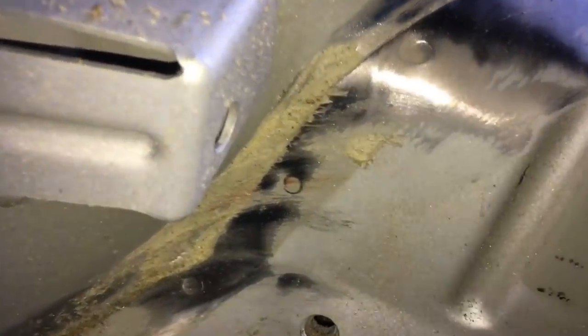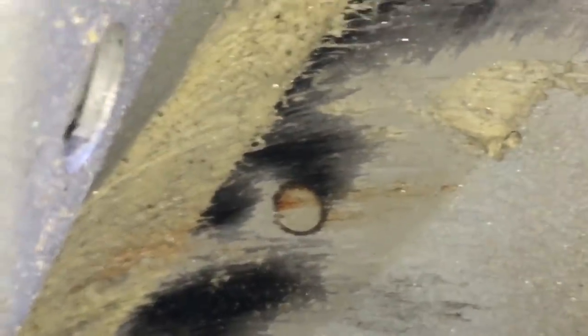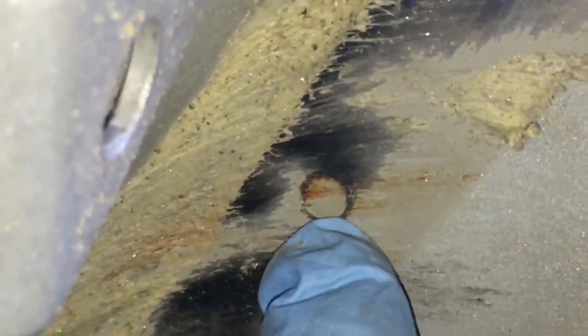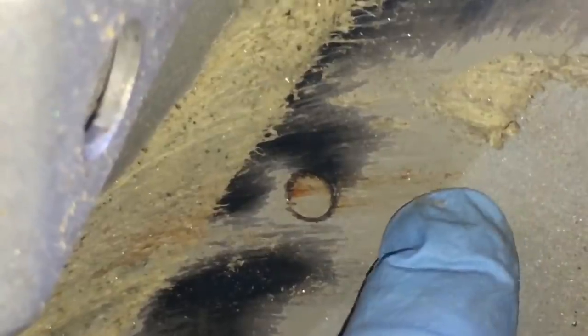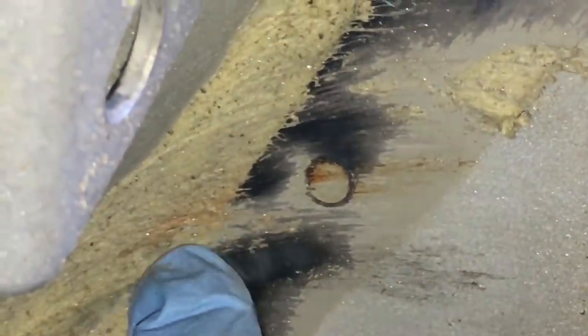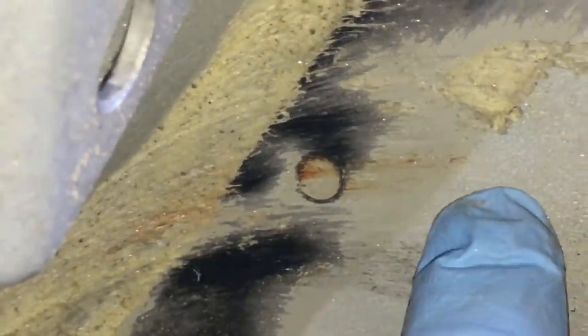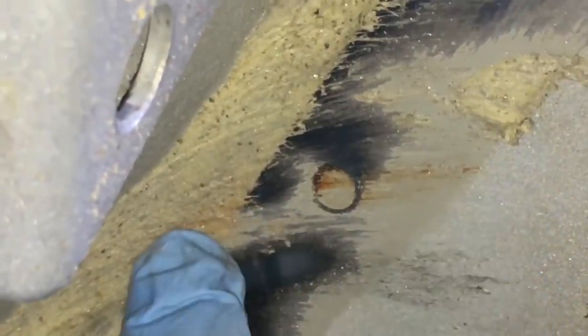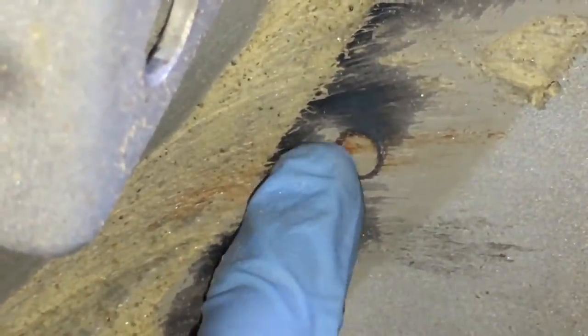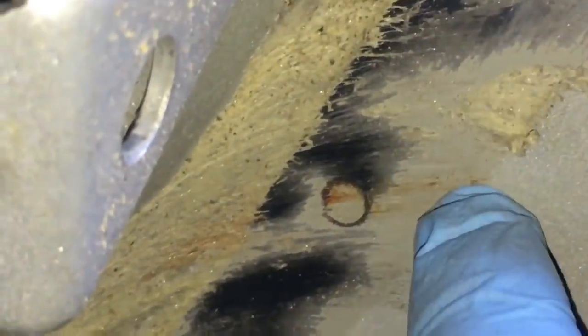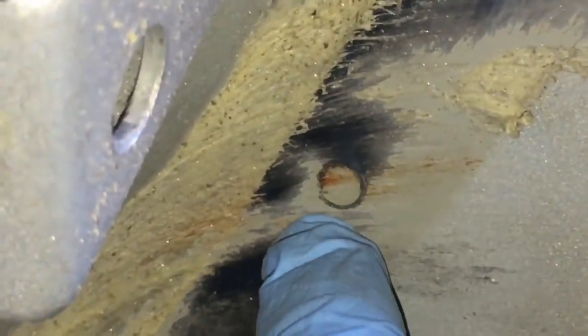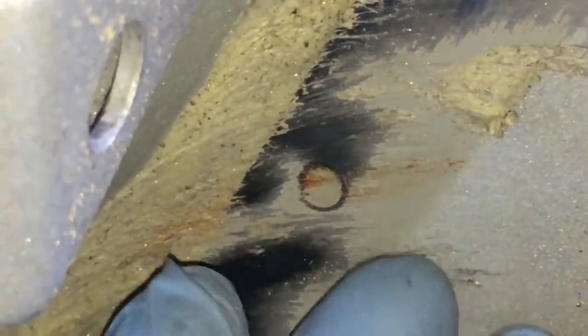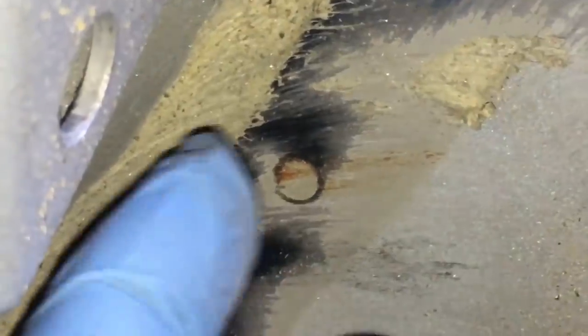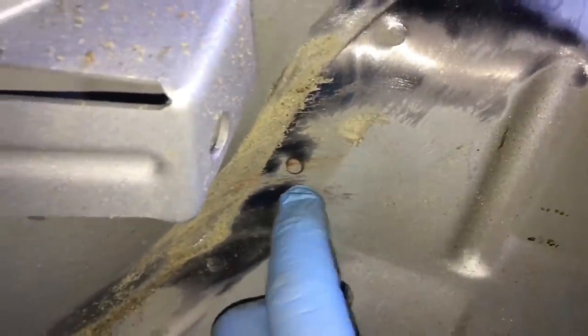This one's the original shape, and you can see I've just uncovered some rust colour corrosion, and it's swiped through and stained very slightly the seam sealer over here and here where the corrosion's just been brushed through it, and that tells me that there's a crack around there, and moisture within the cavity behind the seat panel has been allowed to get into the crack in the panel and cause that corrosion colour. So that tells us that that spot weld is starting to break.